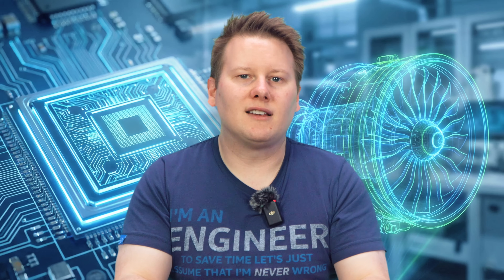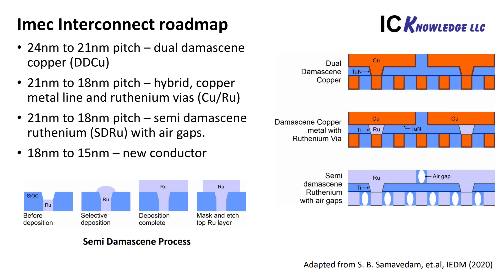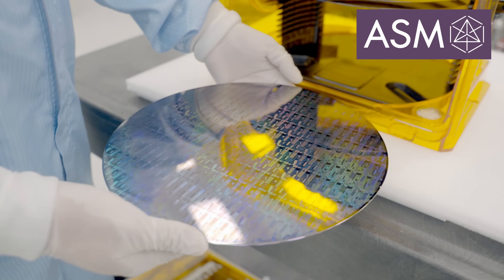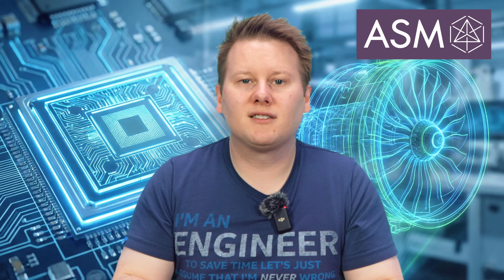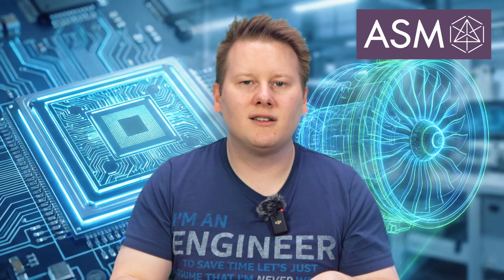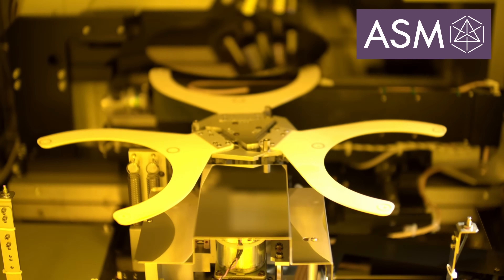All this matters at the interface — the boundary between metals and insulators that sets key parameters like contact resistance, barrier performance, and long-term stability. With that selective flow, you can lay down particular metals like cobalt or ruthenium only where they're needed, without creating any voids. The most reliable route is ALD chemistry, which naturally prefers one surface over another. Today's sponsor ASM has been deeply involved in this for years through their high-k dielectric and metal gate work. The ALD process can grow work function tuning layers on a prepared metal gate stack without unintentionally thickening the surrounding dielectrics. The result is a cleaner interface profile, lower contact resistance variation, and fewer downstream corrections — which ultimately shows up as higher yield and cheaper chips.